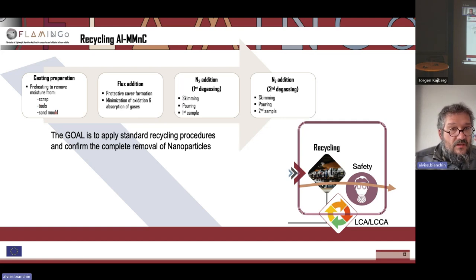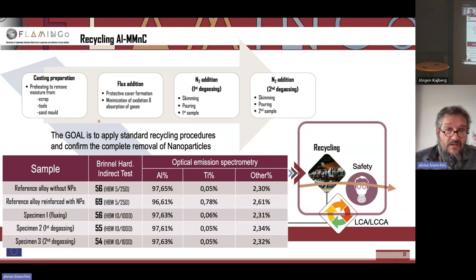So the standard procedure considers an initial melt with the removal of scrap and the flux addition to form a protective cover and minimize the oxidation of the melt, and then skimming a couple of times with the addition of nitrogen in the form of tablets. What we end up with is a billet on which we can perform some characterizations. The two main characterization methods that we used are the hardness test, which is an indirect way to measure if nanoparticles are still there, since they affect a lot the overall hardness of the material.